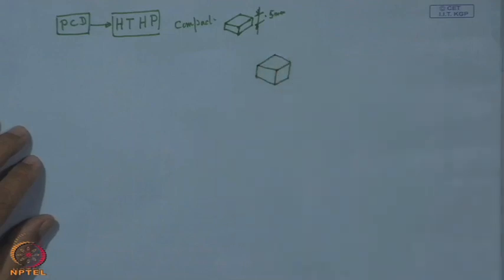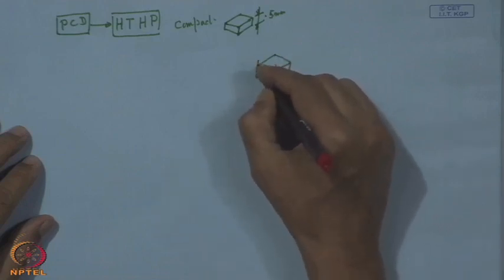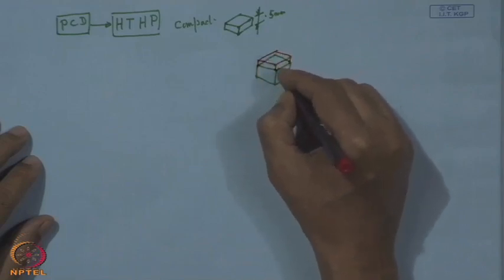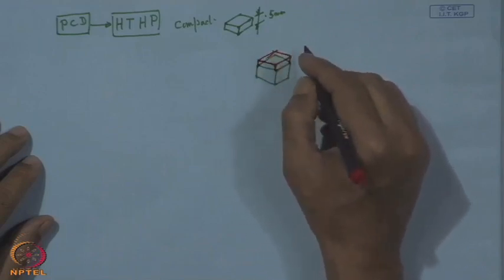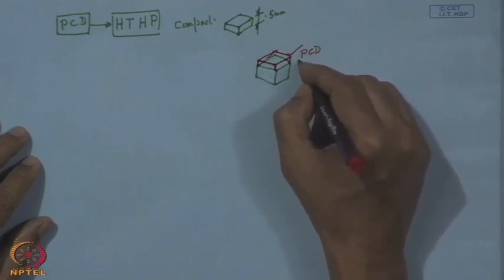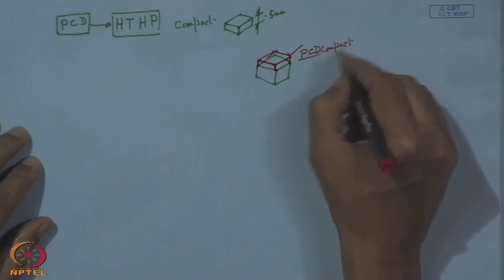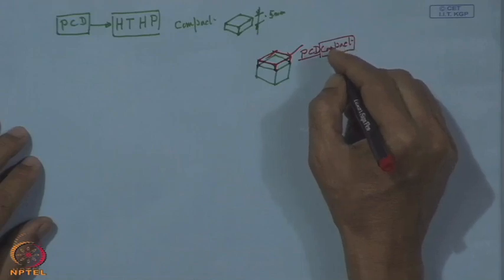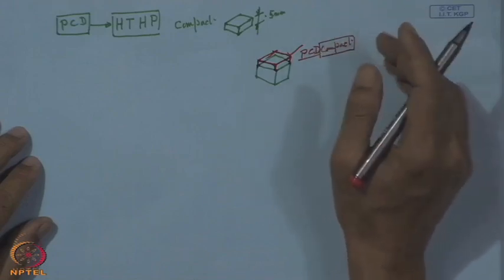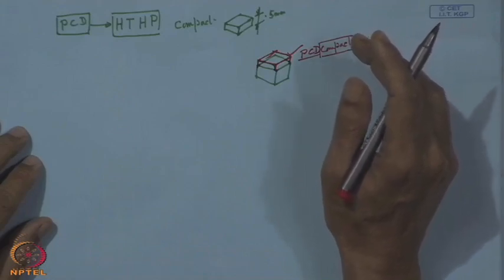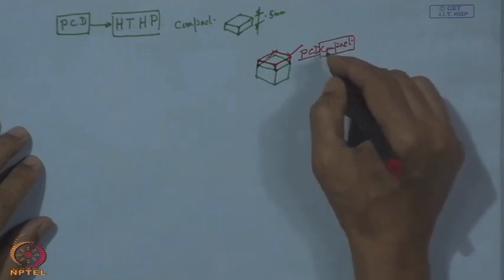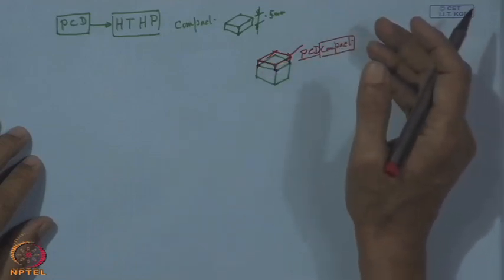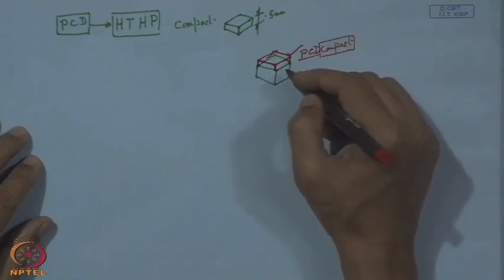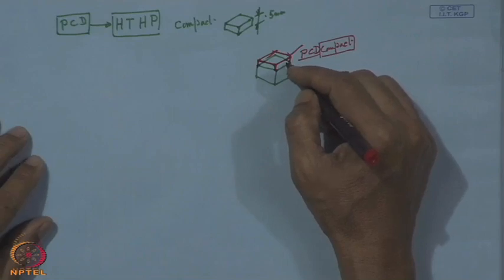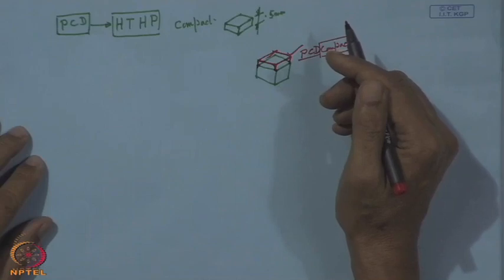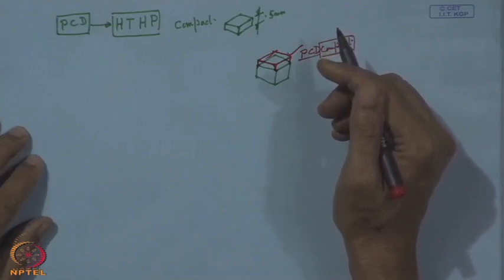On this is brazed, so this is actually the tool. So, this is called polycrystalline diamond, this is the PCD compact. Now, the greatest advantage of this PCD over natural diamond is that it has multi-directional crystallographic orientation. So, the average toughness of this compact is greater than that of natural crystal, and this can be used for various heavy cut machining, where we expect high cutting force and the machining task is a little more difficult.